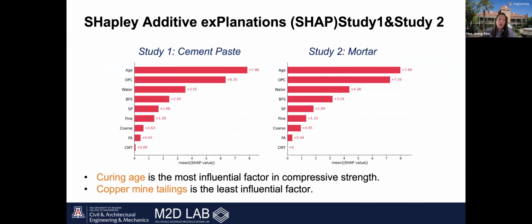And the SHAP results were used to identify which factors have the greatest and least influence on compressive strength. And for both study one and study two, the results show that curing age is the most influential factor, while CMT has the least influence on strength. And in study 2, the effect of copper mine tailings is even smaller than in study 1, indicating that their influence on the overall strength of the mortar is limited compared to other mix design parameters.